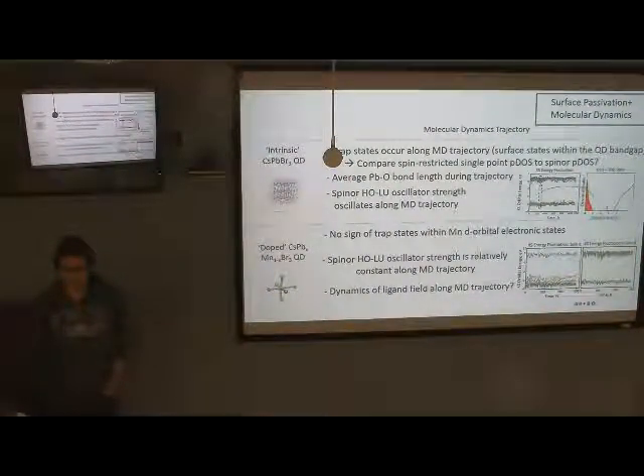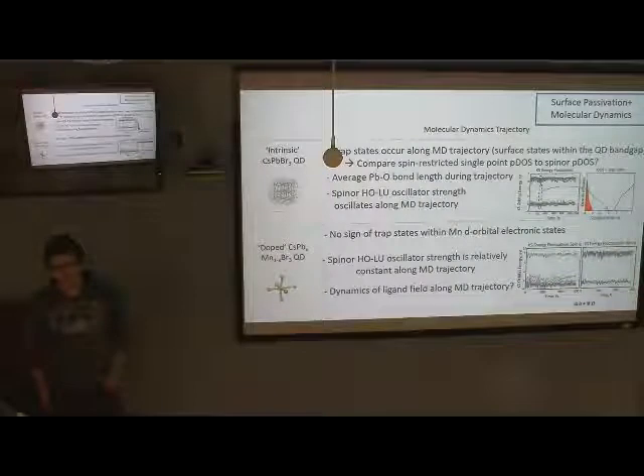I think that's how I plan to process the data, because in an Excel spreadsheet you can choose nearest neighbors by just taking the shortest magnitude. You can take this and Fourier transform directly from the bond distance, but then you probably will have a lot of noise. That's why you can ask Levi. I think he was doing the autocorrelation function between each nearest neighbor, and then Fourier transform from the autocorrelation function, to get rid of a lot of noise, so your spectra becomes much smoother, with very clear peaks. I'll have to talk to him; I'll just send an email to ask.